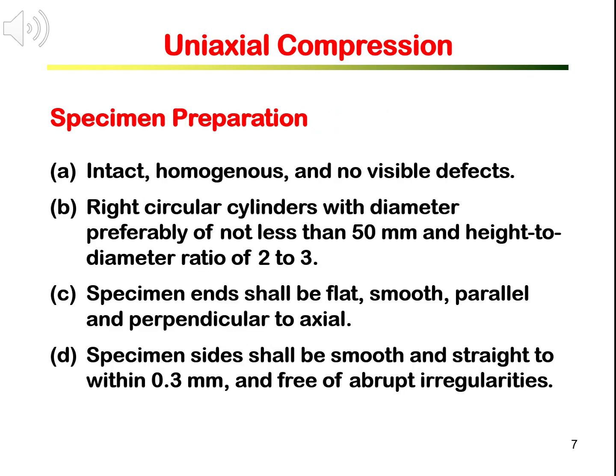Now let us start with specimen preparation. You should select the specimens carefully to make sure the specimens for testing are intact, homogeneous, and have no visible defects. If you are selecting the specimen from rock cores, make sure the portion of core you cut for testing is good, solid, and intact, with no cracks and no other discontinuity features.